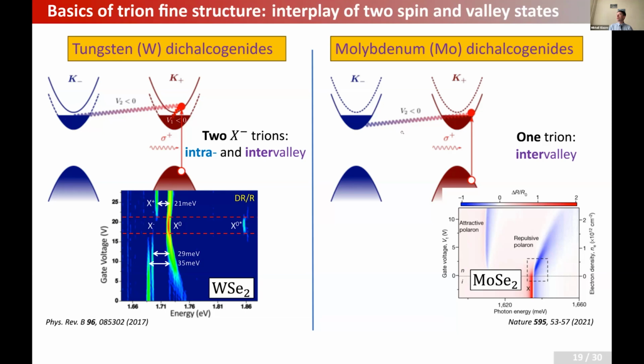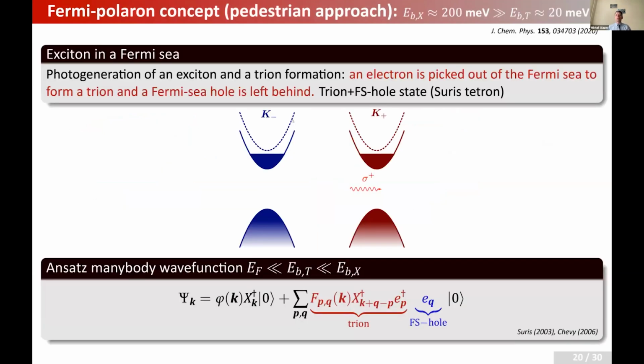In molybdenum disulfide, the optical transition rules are slightly different. Actually, just the order of conduction subbands is different, and that is why there is just one trion line here. Anyway, the question is how to describe this system properly. And this is a very simple idea, again proposed by Robert Suris back in the days at Ioffe Institute. You create the exciton. Now this exciton interacts with the Fermi sea. Let us assume that you have just a simple situation, a molybdenum-based structure, so the bound state can be only with an electron in the opposite valley. Otherwise, just the Pauli principle blocks it.